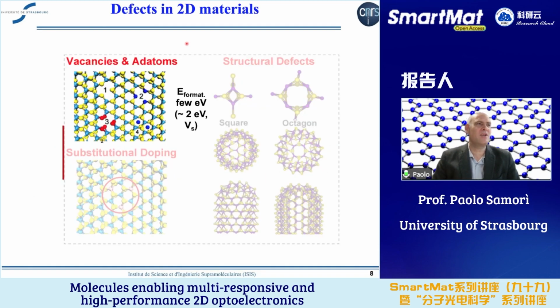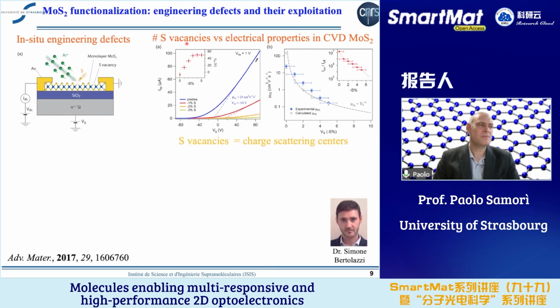And now everything is based on the fact that 2D materials are defect-rich. So defects are, on the one hand, if you're looking purely at the electronic application, you can see some negative aspects related to defects. But on the other hand, defects are sites that are more reactive. And so as more reactive sites, these are ideal for any kind of controlled chemical functionalization.